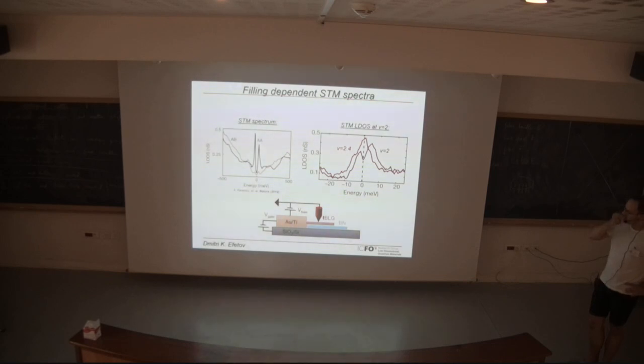But now, since we can tune the filling factor, we can tune the gate. What people have done is zoom into one of those bands. Basically, they have zoomed into this AA lattice site here and filled the system to a filling factor of 2. As you can see from the STM spectra, they can observe a gap exactly at filling factor 2, which is, for example, not present at filling factor 2.4. Again, this is direct evidence that there is an energy gap forming exactly at filling factor 2 and not at other filling factors. So this is, I think, so far the best evidence that locally we have these interactions kicking in.